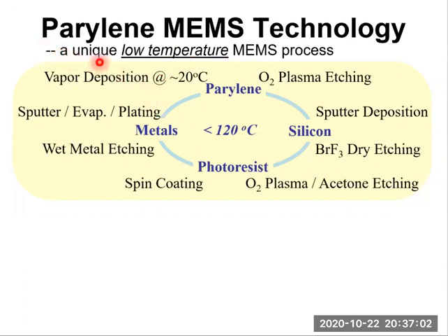This is a unique low temperature MEMS process. Since parylene can be vapor phase deposited at room temperature, 20 degrees C, and it can be etched by oxygen plasma, almost room temperature. And the silicon can be sputter deposited as a sacrificial layer at almost room temperature, and be etched by bromine trifluoride or xenon difluoride, again at room temperature.